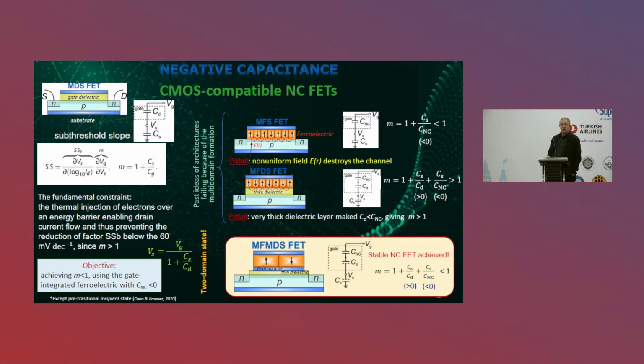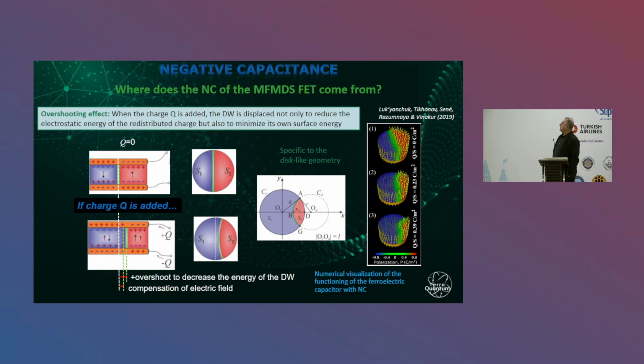Now, we know pretty well from the school course that negative capacitance cannot exist. This is like the law of energy conservation. And nevertheless, we have shown that it can very well exist. If we take a small nanoparticle, about 20 nanometers in size, we can find out that this nanoparticle is split into exactly two domains.